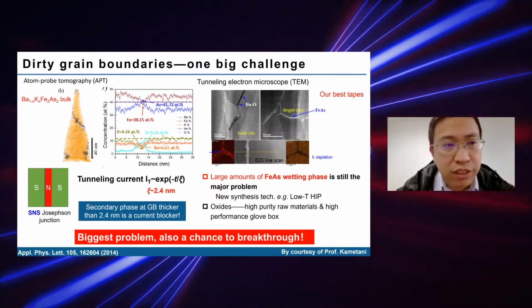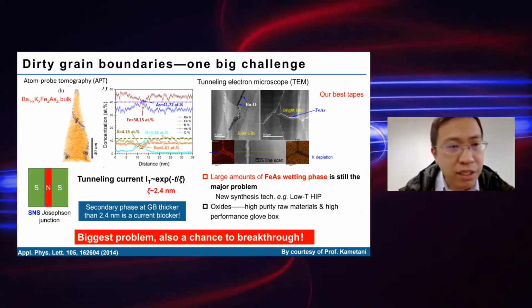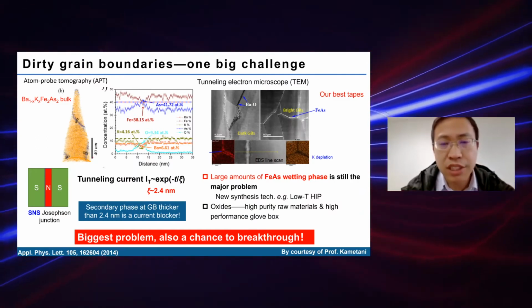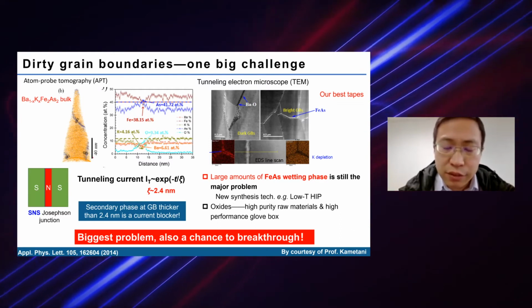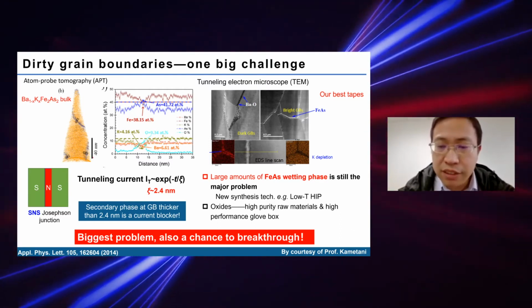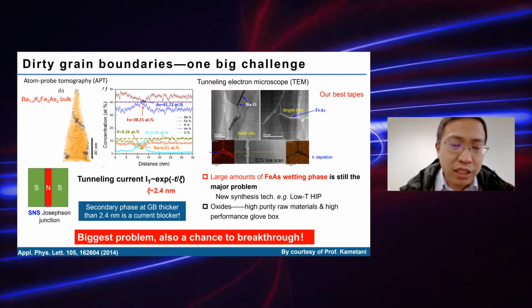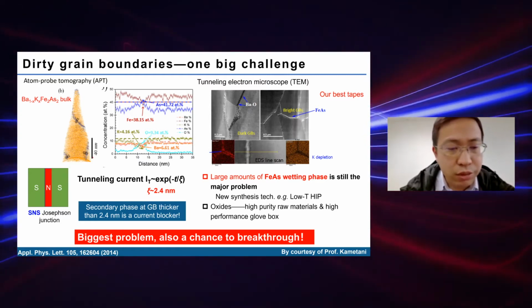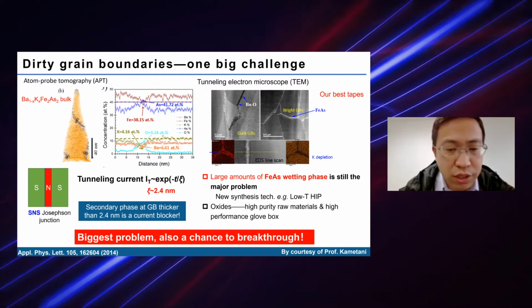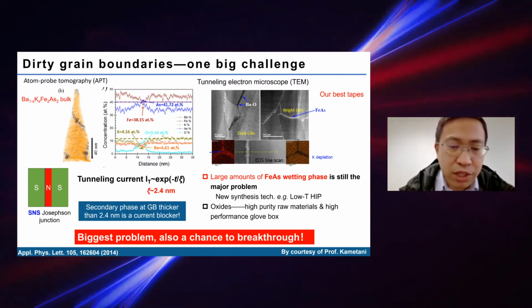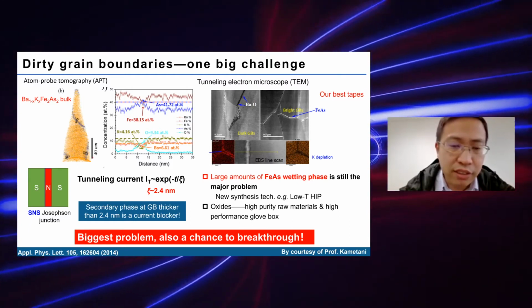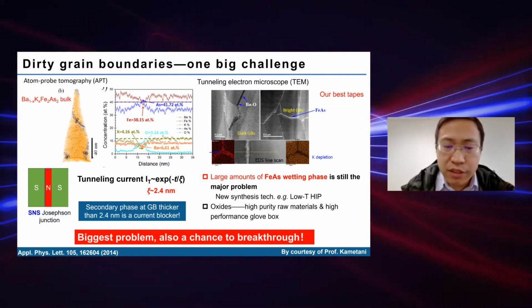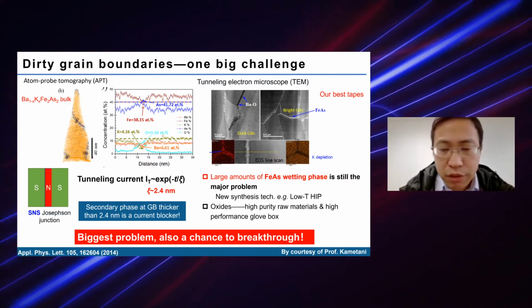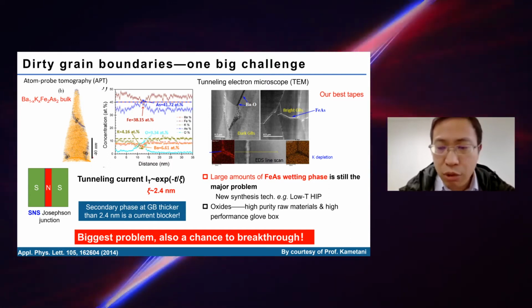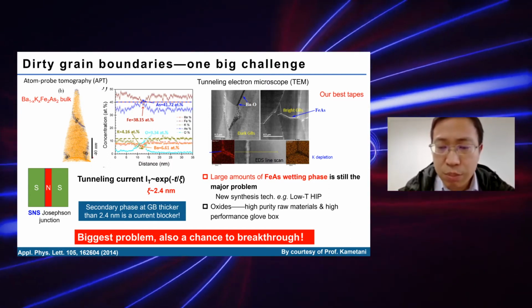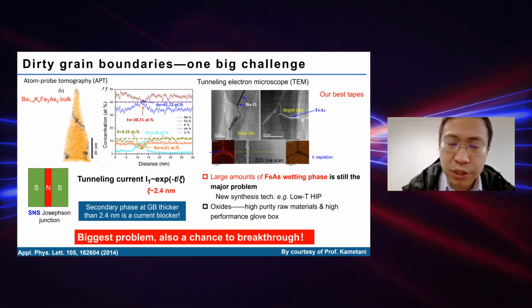Another challenge is grain boundaries, as evidenced by atom probe tomography or TEM. They found there are large amounts of iron arsenide wetting phase, which actually makes the grain boundary into an SNS or SIS junction, or even worse when the grain boundary is thicker than the coherence length. So this is a great challenge, but also when we solve this problem, I think the Jc will be largely increased to a new level.